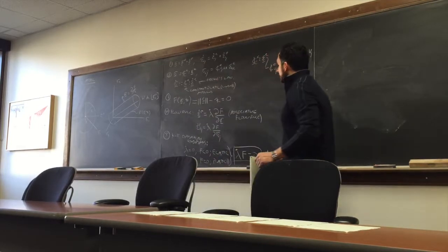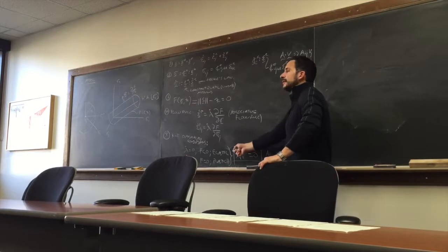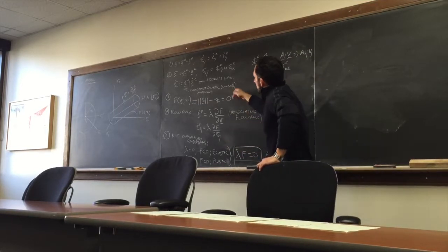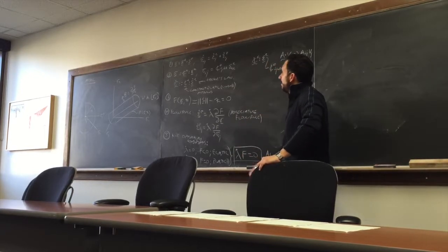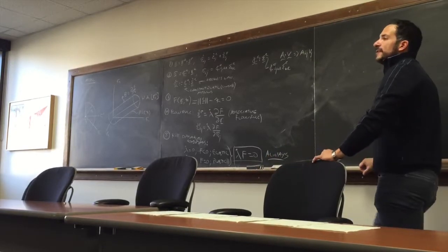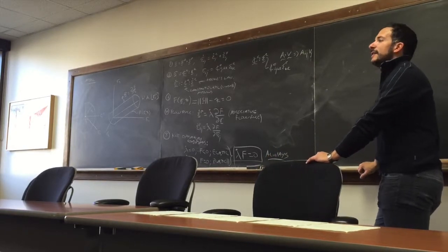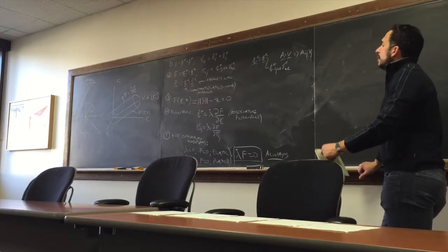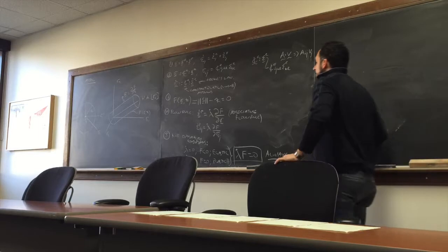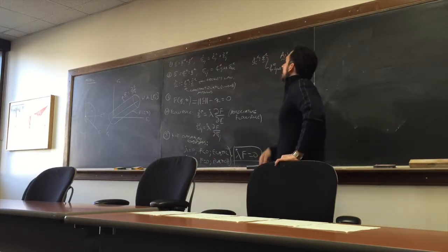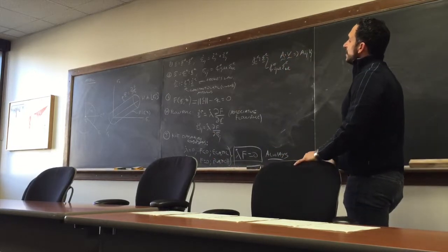Of course, in plasticity, you're not interested in the case when lambda dot is equal to 0 because that's elasticity, that's a trivial case, and none of these things apply. You just apply your elasticity and you're out of it. So in your code, the first thing you're always going to evaluate is, am I elastic or am I plastic? That's just a yes or a no. And if you are plastic, then you know that this applies. Your F must be equal to 0. Your lambda dot must be greater than 0, and then the whole name of the game is to find lambda dot.